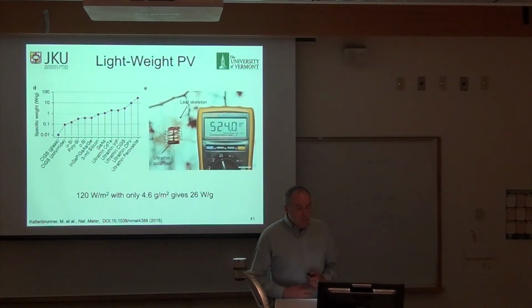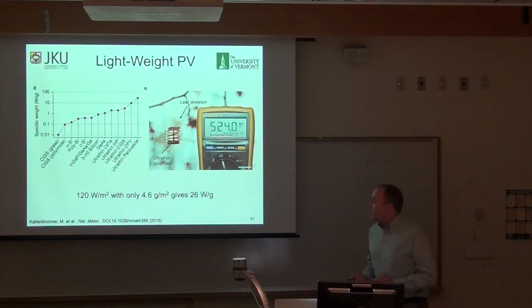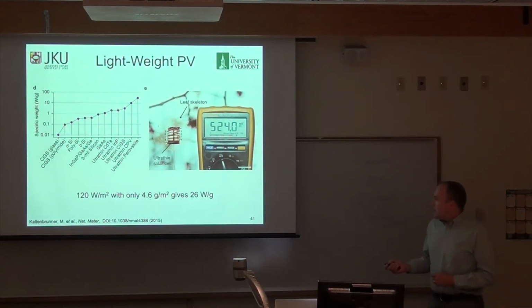So we made these ultra-thin solar cells, and they are 12% efficient. If we put them under one sun illumination, we get 120 watts per meter squared out of the devices. But they only weigh 4.6 grams per meter squared, which means they give out 26 watts per gram of solar cell. This metric, specific weight, the watts per gram of the solar cell, is useful for things like space applications or military applications.